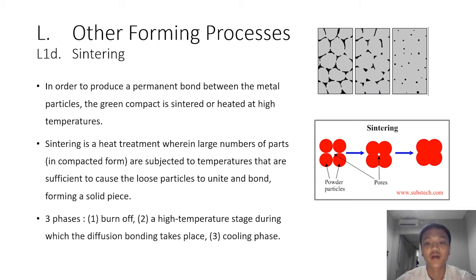For iron-based parts, the temperature ranges from 1850 to 2100 Fahrenheit. Copper, bronze, and brass parts allow somewhat lower temperatures. The last phase is the cooling phase, which lowers the temperature of the sintered workpiece while maintaining the controlled atmosphere. This is the illustration of the particles. This is before sintering, and this is after sintering.